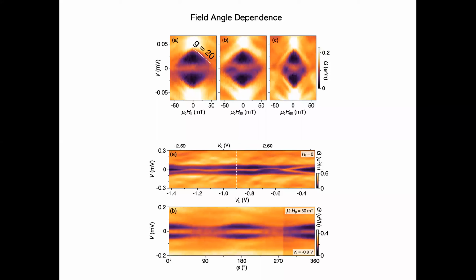So I'm a bit puzzled. I thought that from the previous experiments, we can reasonably conclude that the field misaligned with the wire axis is actually much worse. And even 100 millitesla misaligned, a field that is perpendicular to the wire, would basically suppress all of the superconductivity and basically destroy it. Now this seems to be in contradiction.